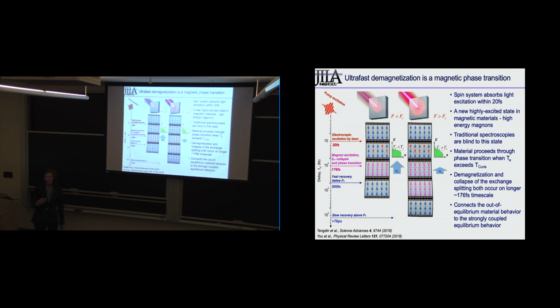But there is no complete theory, although Martin Weinelt, who's from Berlin, had a theory paper where he proposed that this should happen, because if you look at electron-electron exchange scattering, that can happen very quickly. Electron-electron scattering is sub-femtosecond, and they can flip a spin in a few femtoseconds, if they are a few eV above the Fermi level. So in other words, we're not violating any physical law.